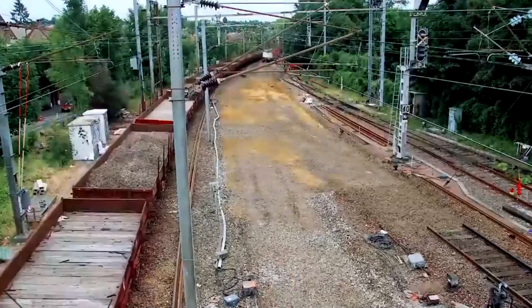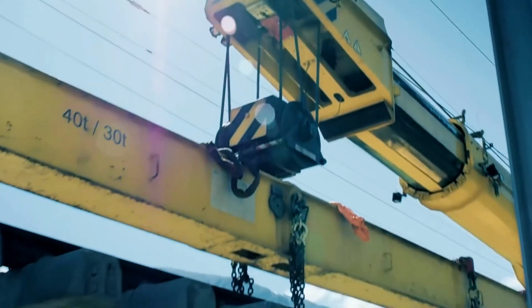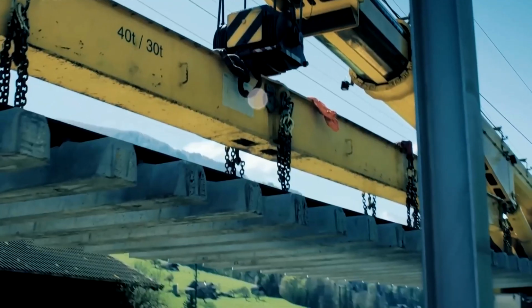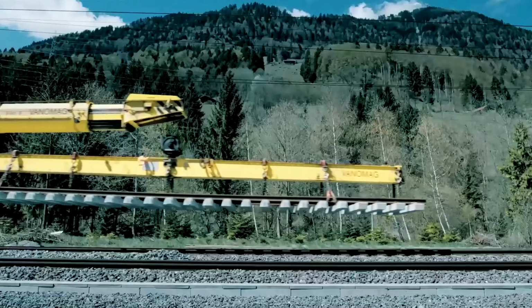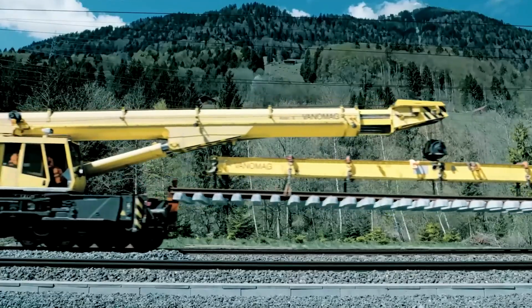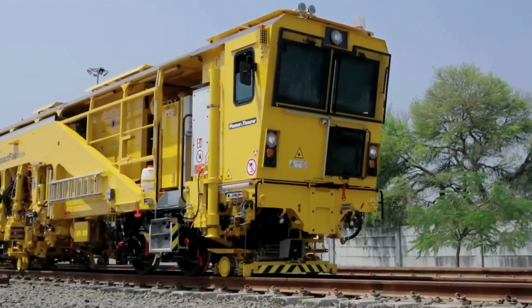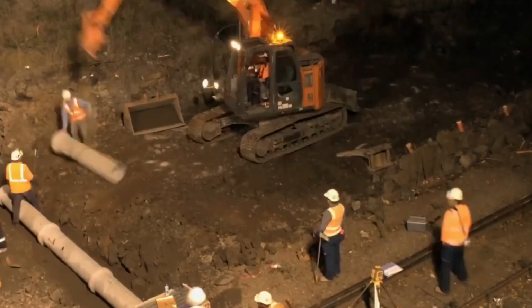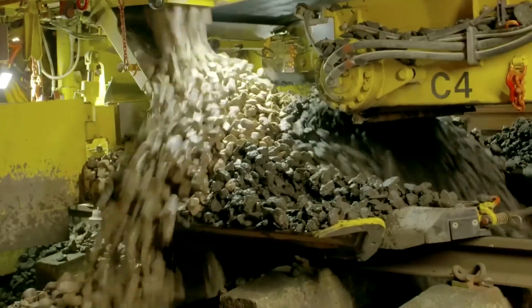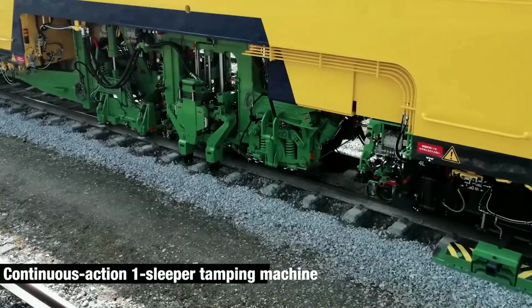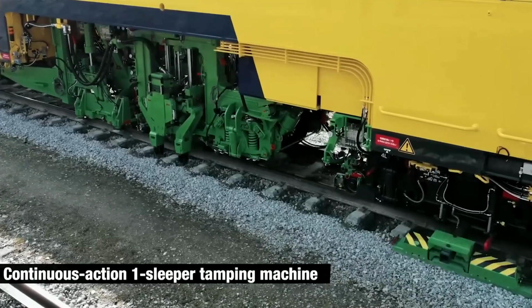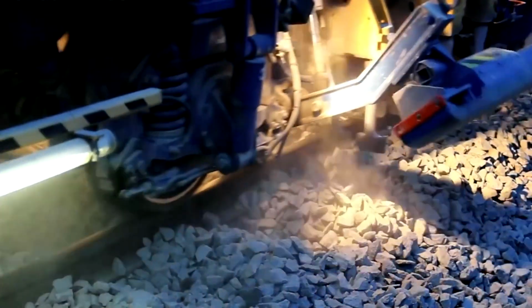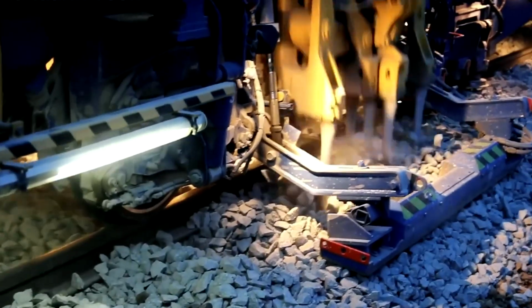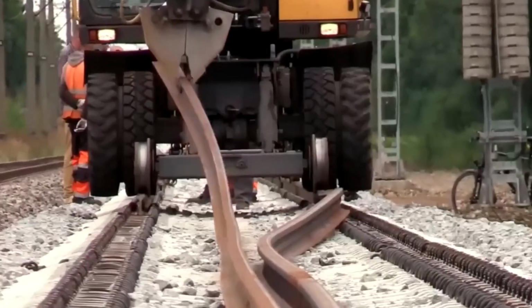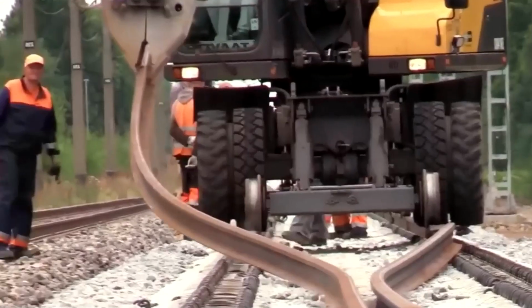Once the entire rail line has been welded and ground smooth, the final inspection begins. Engineers use an ultrasonic flaw detector to scan the rails, detecting microscopic cracks or internal voids hidden deep within the steel that are invisible to the naked eye. A track geometry car then measures elevation, tilt, curvature, and gauge width with precision down to 0.02 inch. Any deviation beyond tolerance is corrected immediately using tamping and alignment machines.